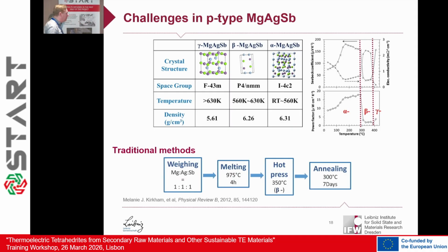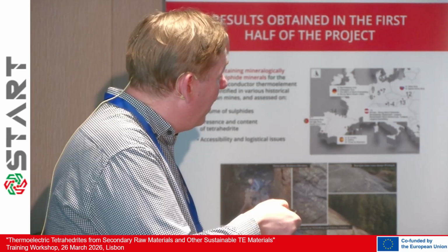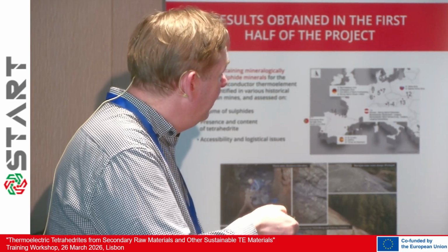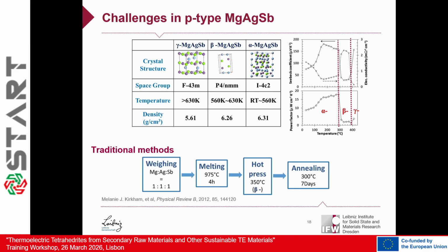Here, one comment about the phase transition in magnesium silver antimonide. Up to 300 centigrade, this works quite nicely. You have the alpha phase of magnesium silver antimonide, and this is very robust, I would say. If you go beyond 300 centigrade, you have the transformation to the beta phase. This is still okay, but you don't want to reach the gamma phase of magnesium silver antimonide, because it's not really reversible, and therefore you try to stay away. So you should not heat your device beyond 300 centigrade.